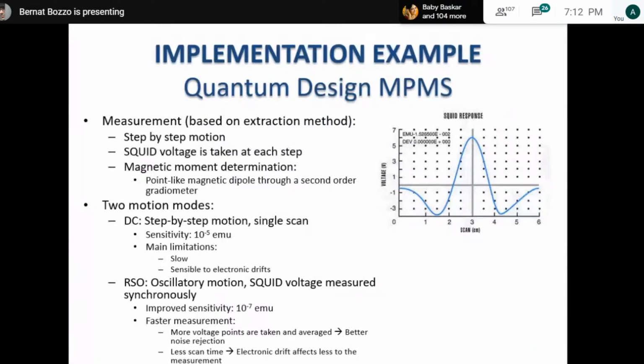In order to overcome these limitations, we use what is called RSO motion. Basically, it's an oscillator. It is based on how we treat the sample signal through this second order gradiometer. We improve the sensitivity by an order of magnitude, down to 10 to the minus 7 emu noise floor, and it is a faster measurement, basically because we have more voltage readings taken during this measurement. We have better noise rejection since we have more averaging.